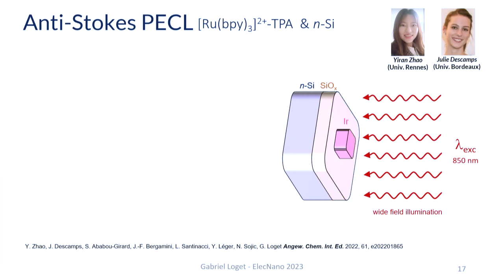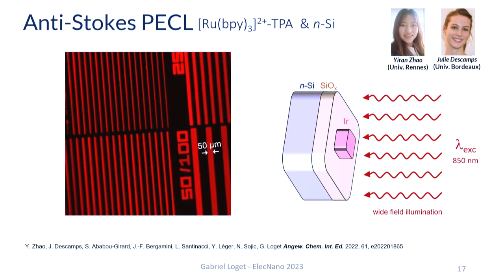Another way to do a localized PECL is to use a patterned electrode, to illuminate the whole photoelectrode area homogeneously with the IR light, but instead of using a full metal film, we just use a metal pattern. So the photo-generated holes will be, because silicon oxide is an insulator, collected at the metal thin film, and the reaction should occur at that place. And this is what happens.